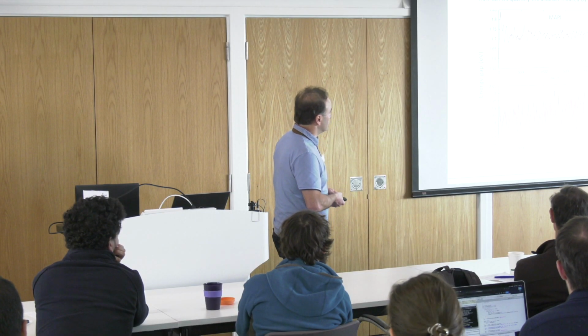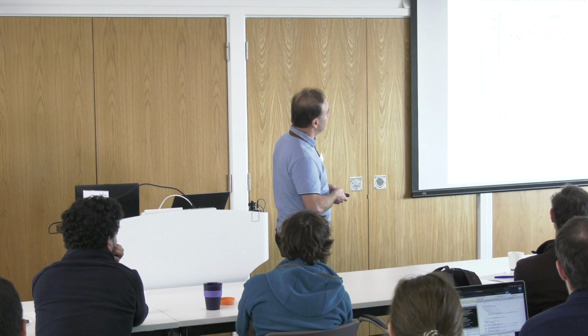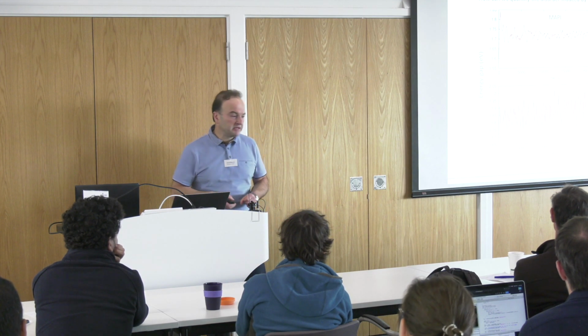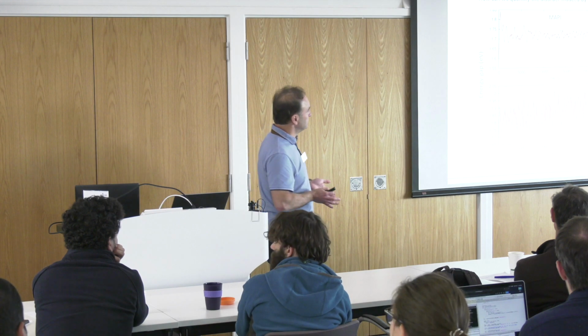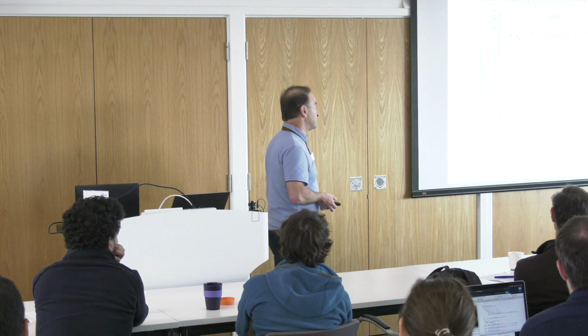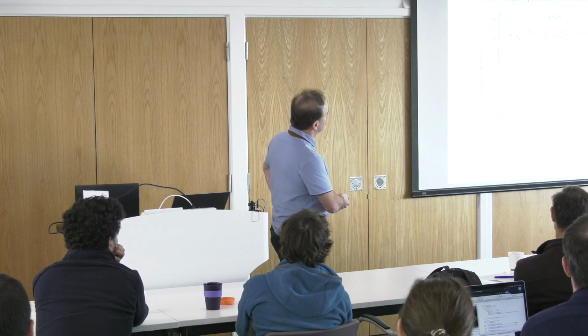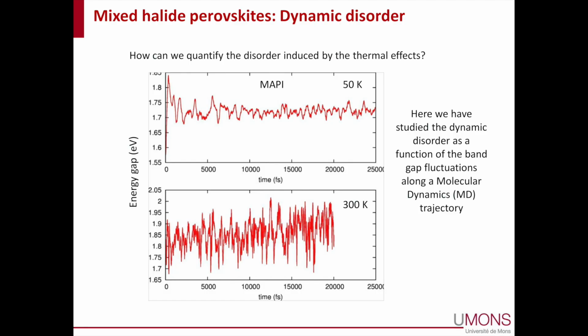So we have started those simulations. They are very expensive calculations. These are Born-Oppenheimer molecular dynamics simulations, so quantum dynamic simulation, but where we solve classical trajectories. And we track the energy band gap as a function of time. This is shown for MAPI for 2 different temperatures. You see those fluctuations in the band gap, which get, of course, much larger at room temperature because you have larger amplitudes of the motion.